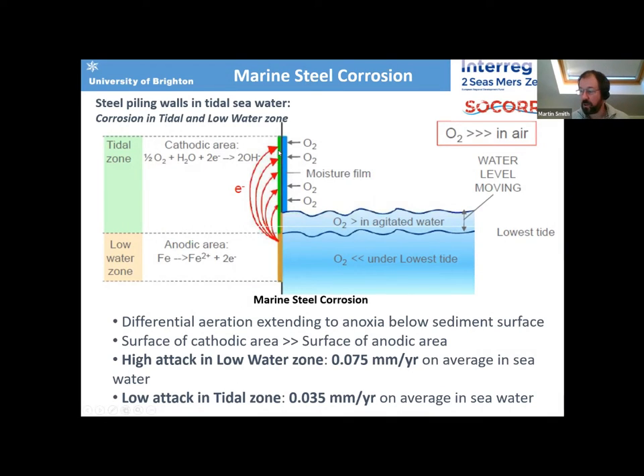So if we look at an example like this, where we have differential aeration extending from fully atmospheric oxygen levels down to anoxia, we get high attack rates in the low water zone, up to about 0.075 millimeters per year. And that's at least double what we'd usually get above the tidal zone, immediately above this area. So we've got enhanced corrosion rates on intertidal or low water steelwork anyway, because of the electrochemical environment.